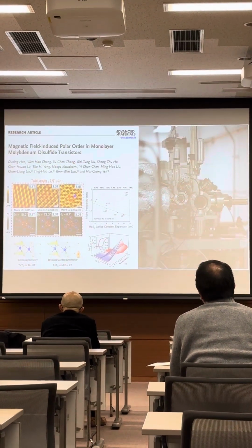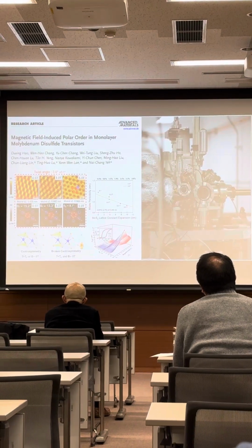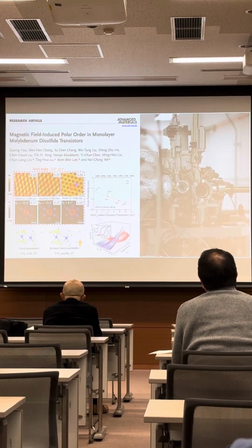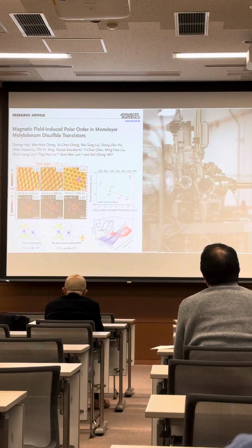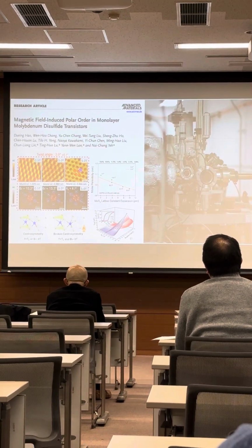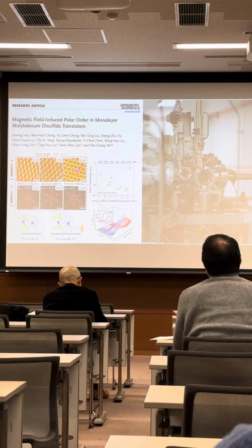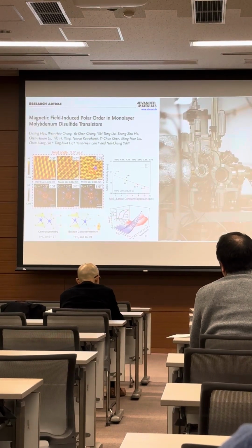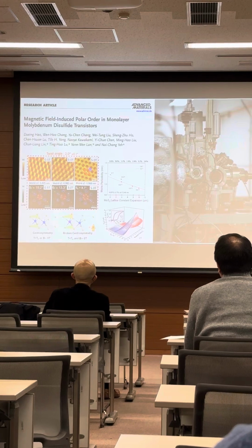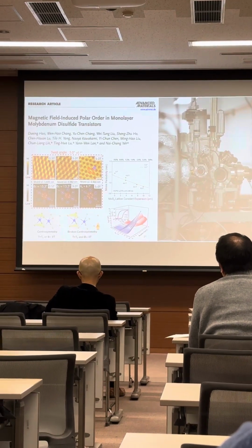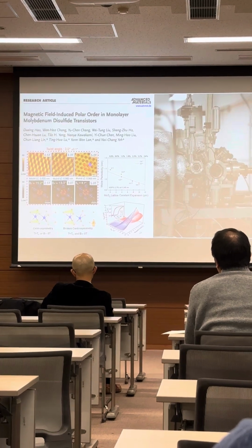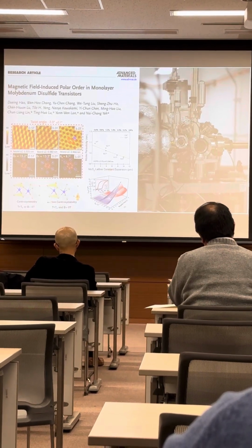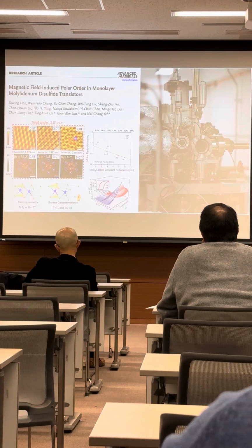So now for the final summarization. In this work, we have confirmed that MoS2 lattice will experience roughly 1 to 3% expansion upon out-of-plane magnetic field applied from 0.5 Tesla to 5 Tesla, which results in an obvious difference in the relative angle phi and the Moire periodicity. This result is also matching with our collaborators' Raman spectrums, and lattice expansion on the rigid substrate with expansion coefficient mismatch will lead to a flexoelectric effect, which gives rise to out-of-plane polarization, and therefore to our observation of the magnetic field-induced ferroelectric hysteresis behavior.